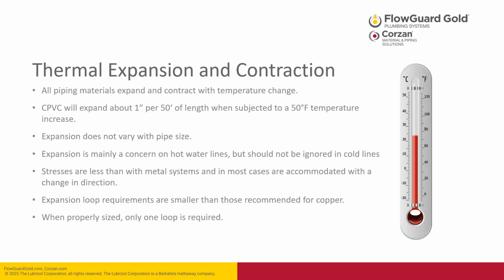It is important to note that when you're determining how much temperature change a system will experience, it must be calculated relative to the temperature at the time of installation. For example, if you're installing a hot water system that will operate at 140 degrees Fahrenheit on a 40-degree day, that is a 100-degree temperature change. Likewise, if you're installing a cold water system that will operate at 60 degrees Fahrenheit on a 120-degree day, you will have a 60-degree temperature change in that system. However, in that circumstance, the pipe will contract as it cools down.